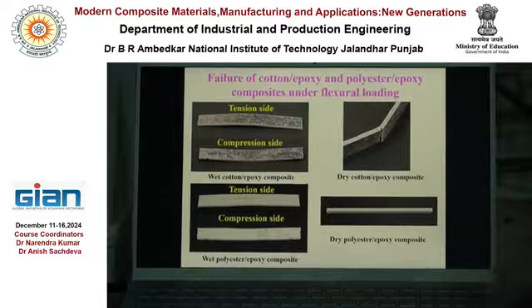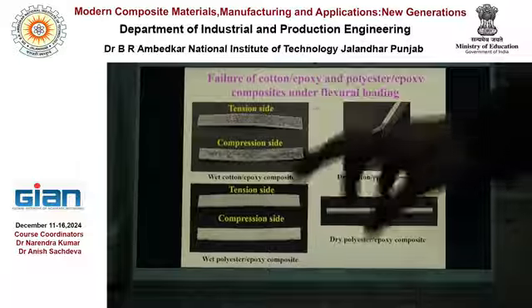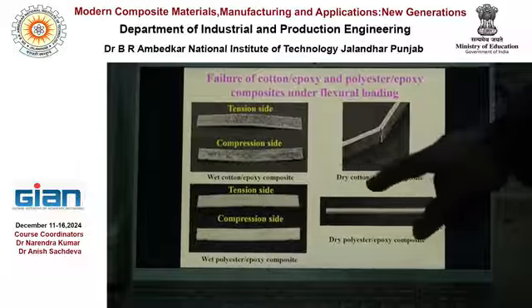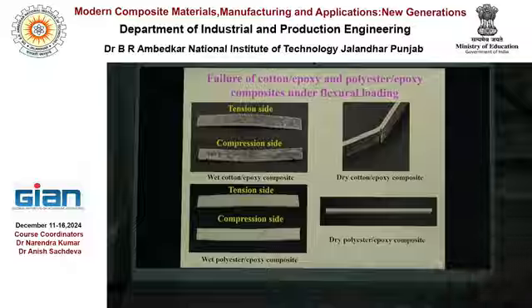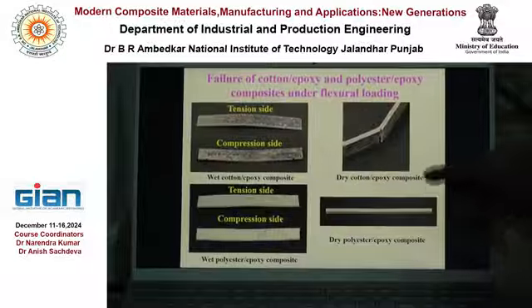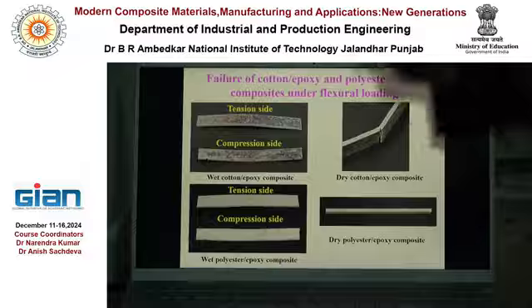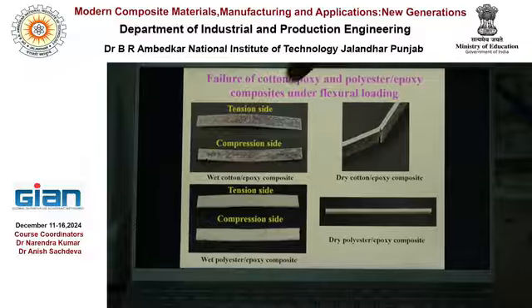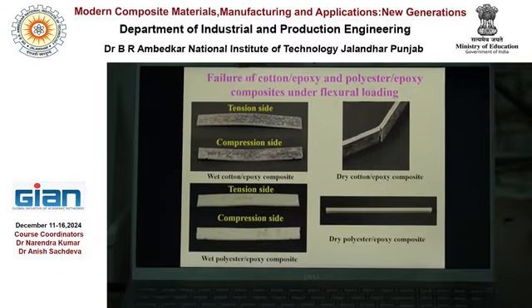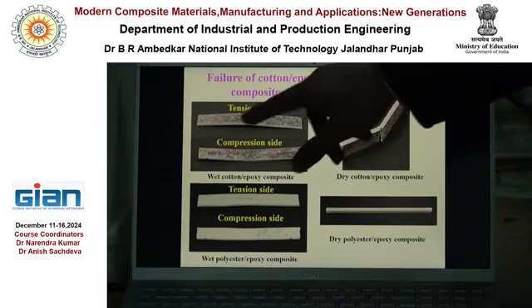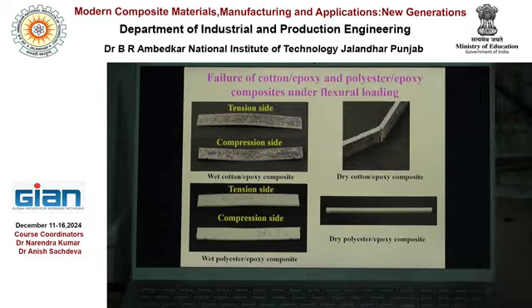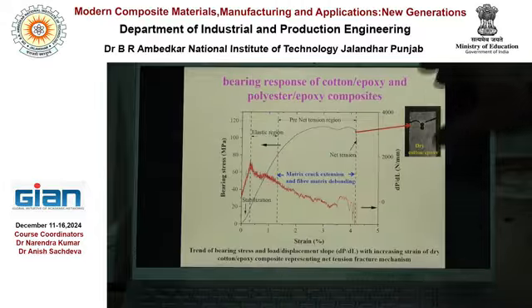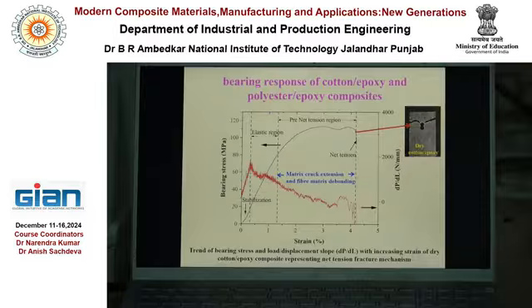So after conducting this test, we can again go for the mechanical test. We have done it for this composite material. You see that for the dry cotton epoxy composite, the material fractures under flexural loading, but after water absorption, it becomes flexible, and we do not see this crack at the tensile side of the composite material. So this is the result of the bearing response of the cotton epoxy and polyester epoxy composite material.